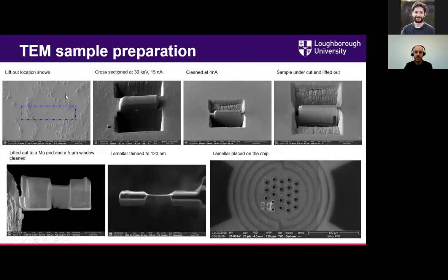using a standard lift out procedure. We gold palladium coated the sample, put some platinum down, and then performed a normal TEM lift out. And then we placed this on the hot stage. You can see down in the bottom right corner the little sample over one of the transparent windows.